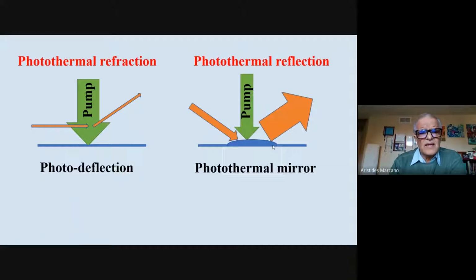And here you have several examples of very well-known photothermal effects, and the most popular I have here. One is the photothermal refraction. When you have one surface, could be a metallic surface, you focus the pump laser, represented by this green. We usually have a green laser for that. And then we send a test laser, a probe laser, and see that the probe laser can be deflected. Sometimes there's some deflection, and people developed that method because it's very sensitive, and the deflection is due to the gradient of the refraction index that happens in the nearby region of the surface.